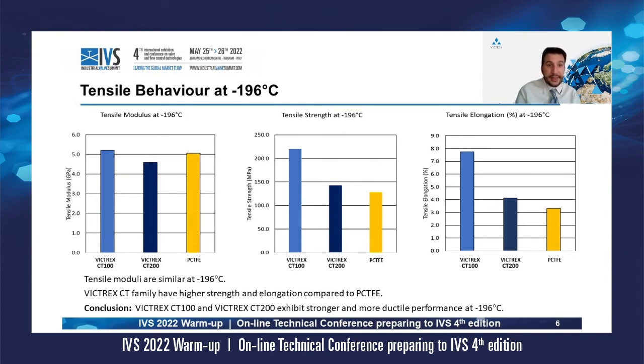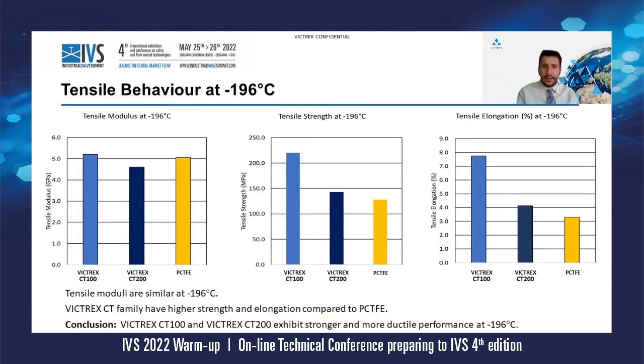For the tensile strength, it's around 220 megapascal, and the tensile elongation of CT100 is around 8%, while the tensile strength for PCTFE is around 130 with about 3% elongation. It's important to underline that an elongation of 8% is a lot, because we're talking about almost -200 degrees, where everything becomes very, very stiff. So an elongation of 8% is really appreciable.